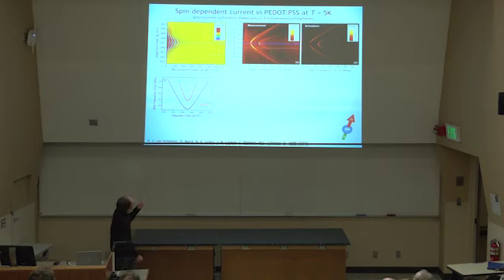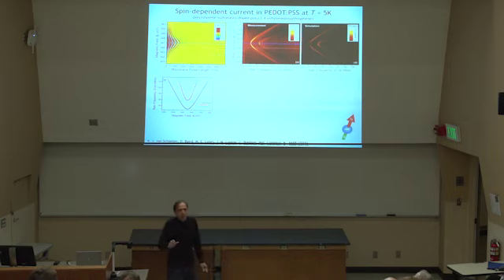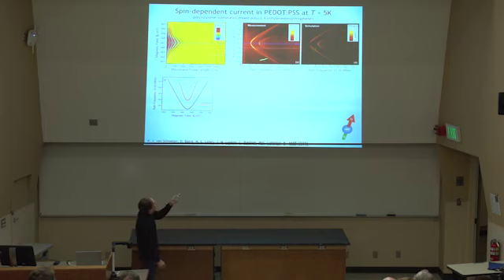What do we learn here from this example? So compare our measurement with the simulation of spin-dependent rates that we prepared really for a super simplified case of two pairs, two spin-1/2 pairs that have absolutely no coupling whatsoever. Coupling is 0. And you see there's a great similarity, but of course not identity between the simulation and the experimental data.